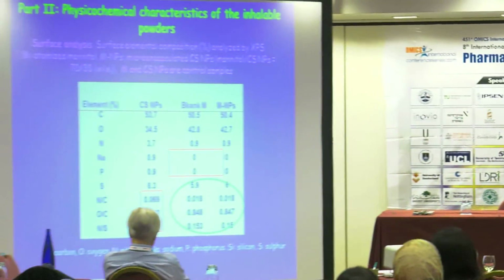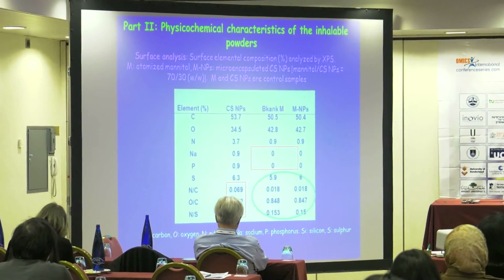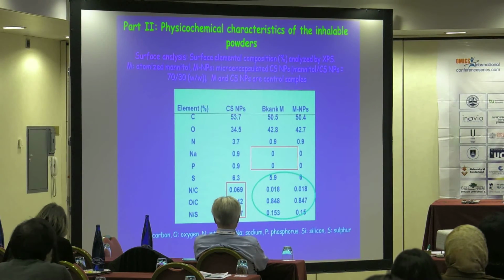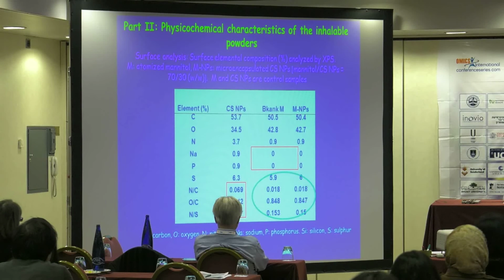Looking at the atomic composition and atomic ratios, we found that the surfaces of the blank mannitol and the mannitol-microencapsulated chitosan nanoparticles had the same surface atomic composition, with the same proportions or concentrations. This means we have only mannitol on the surface. Meanwhile, the non-encapsulated chitosan nanoparticles had different elements and different atomic ratios on the surface, giving another clue that we have only mannitol there, and no nanoparticles adsorbed on the surface.